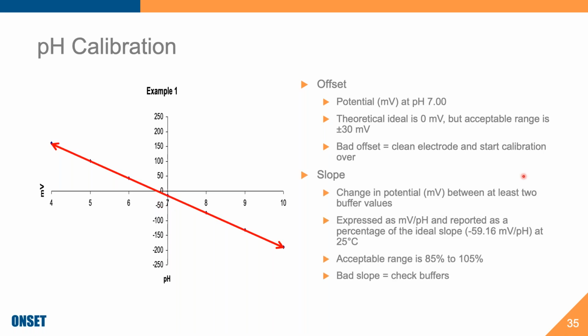Okay, so the second correction factor that we get when we calibrate, and hopefully you get because you're doing more than 1 point, is your slope. And the slope is the change in the potential between at least 2 buffer solutions. And again, we're pretending here that this was done at 7, 4, and 10. It is expressed as millivolts per pH and reported as a percentage of the ideal slope.